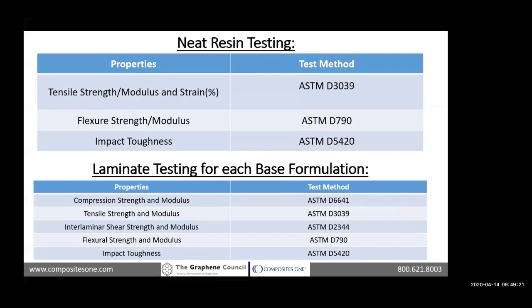I think it's important to understand how we're going to evaluate the graphene. What kind of testing are we going to do? There are two groups we're going to utilize. The first group of testing is just neat resin testing. These are three basic test methods that you see on most epoxy data sheets: tensile strength and modulus, flexural strength and modulus, and impact toughness. I've listed the ASTM tests so that you can refer to them and understand how we'll be evaluating the graphene. And this is just in the neat resin.